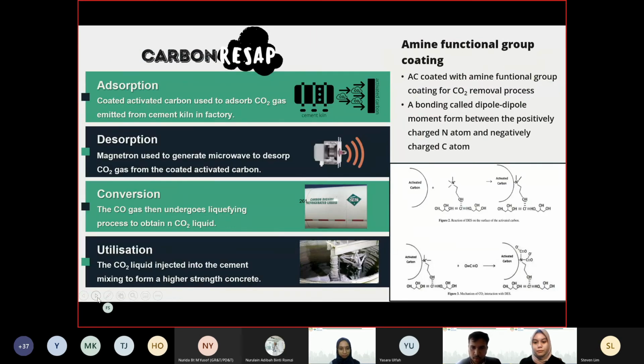Project Carbon ESAP comprises 4 important stages in order to produce the end product. Synthesis of Carbon ESAP starts from adsorption, where CO2 gas is released in a cement kiln, which is captured and absorbed on the surface of AC through its porous structure. It is worth mentioning that the adsorption rate is higher through the application of a coating on the surface of AC. A specific coating that is made of amine functional group is coated on the surface of the AC to absorb CO2 onto the surface.